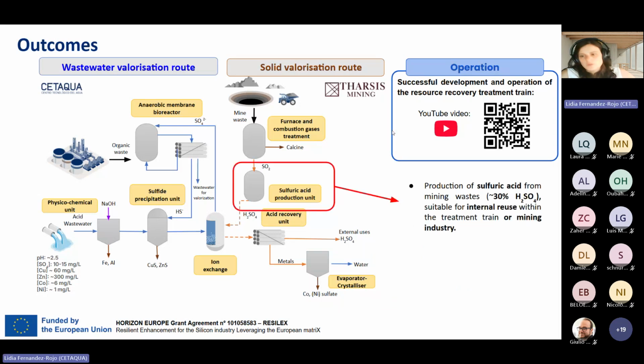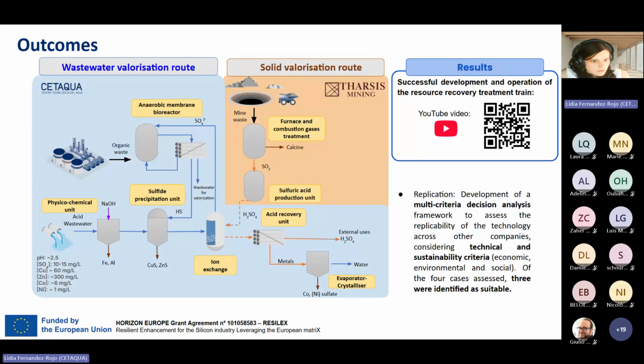And for the solid valorization route, we were able to produce sulfuric acid from mining waste with a concentration of about 30%. And this acid was able to be reused internally within the treatment train or the mining industry. And concerning the second objective, which was to assess the recovered metals and develop a replication plan, we developed a multi-criteria analysis to assess the replicability of this technology across other companies, considering technical and sustainability criteria. And we assessed 4 different places where this train could be upscaled, and 3 of them were identified as suitable.